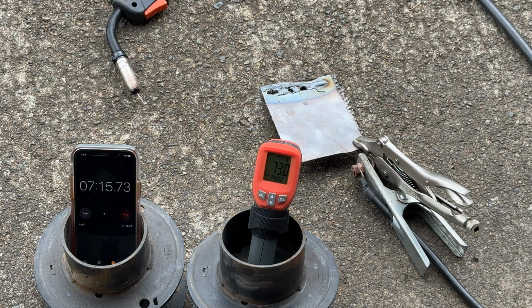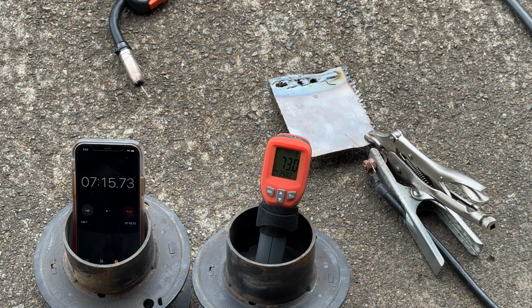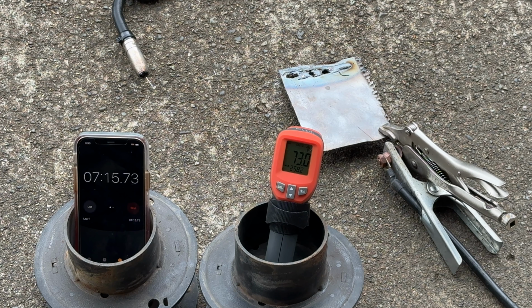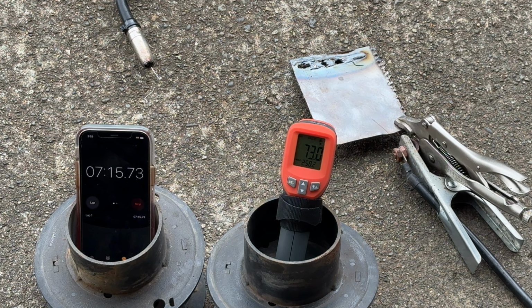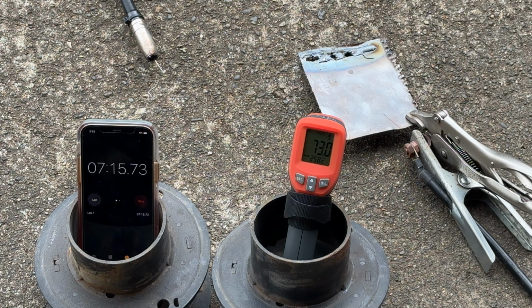7 minutes and 15 seconds is how long it roughly took for this panel to cool down all on its own from 258 degrees down to 73.